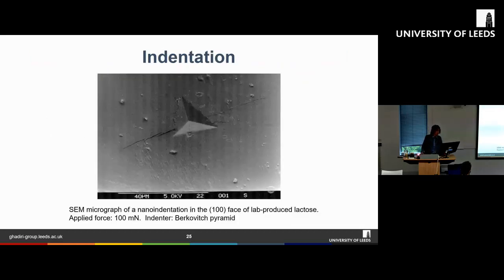So this is an example of an impression made by a Berkovich indenter. The Berkovich indenter has this typical pyramidal shape, and because of its three-sided geometry, it is very easy to machine to a very high precision and very sharp angle. Hence it is highly preferred in the work of nanoindentation.